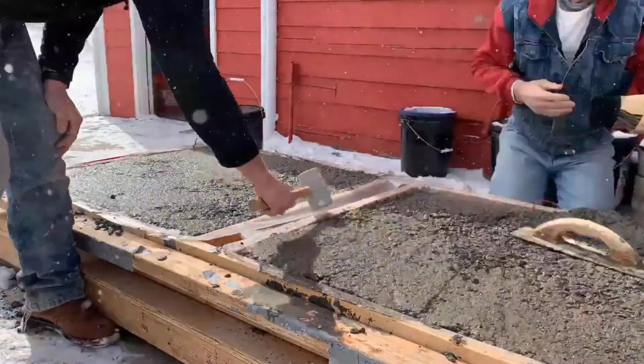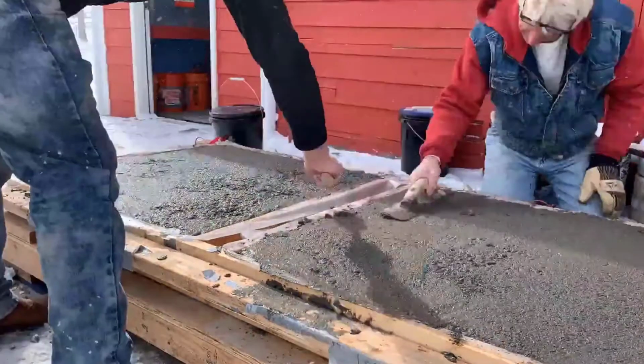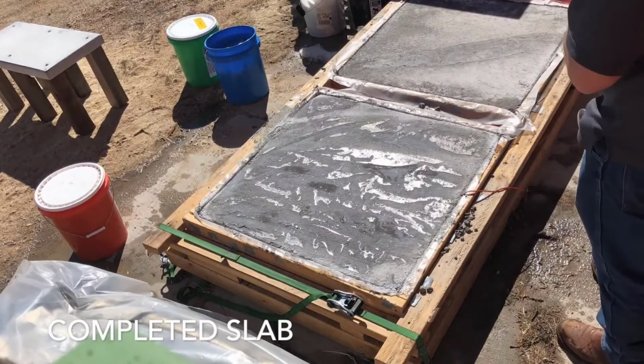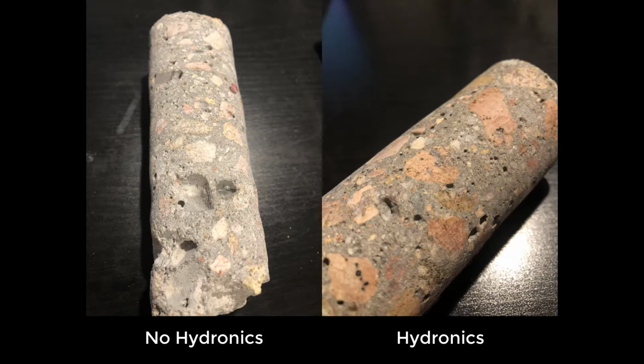From there, we cored out the samples. We did strengths on those samples, and Haley will put the link down below. But what we wanted to go over today was the look of those samples. We cored out some extra samples and kept them off to the side, and that's what you're looking at right now. To the left, we have a sample from the slab that was not heated hydronically, and on the right side you have another sample from the slab that was heated hydronically. So let's go ahead, and this is our overhead shot.